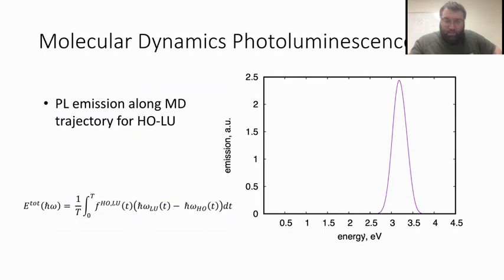And then the next slide, Dimitri. This, just like the slide two slides ago, is photoluminescence, but in this one I was looking at the highest oscillator strength, which was HOMO to LUMO+1. So we see that a lot of the IR emissions in the intensity graph are gone, and the ranges are the same as on the previous graphs. We can assume that was probably some interband interactions occurring. And we once again see the peak right around 3.3 eV for the band gap photoluminescence.